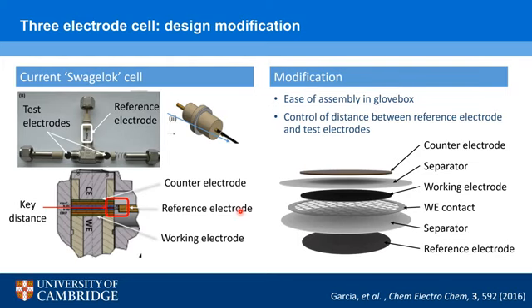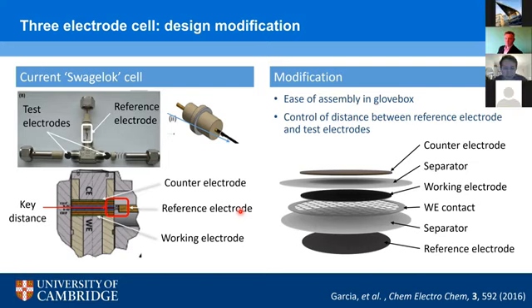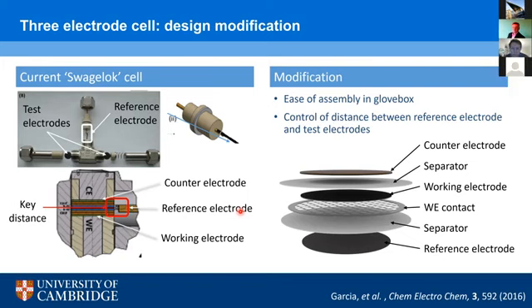One of the things that we would like to try with our design is, at the moment, at the end of the probe, like reference electrode, there's a small piece of lithium. If we could use a larger 14mm standard lithium chip, that would also provide a larger surface area, which would hopefully make the behavior closer to the ideal constant potential that Dylan mentioned earlier. So by changing the order of the components, it would also hopefully inherently make it easier to control the important difference, the key distance between the working electrode and the reference electrode.